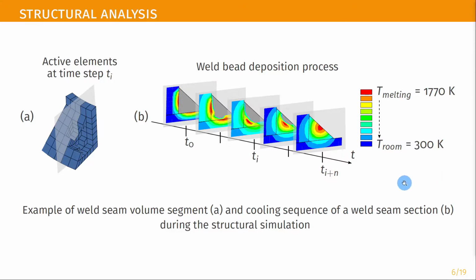From the figure, it's possible to identify a sequential activation of the elements with a temperature lower than the melting point. The result thus obtained represents what is expected from the solidification of a pool of molten metal during the welding process.